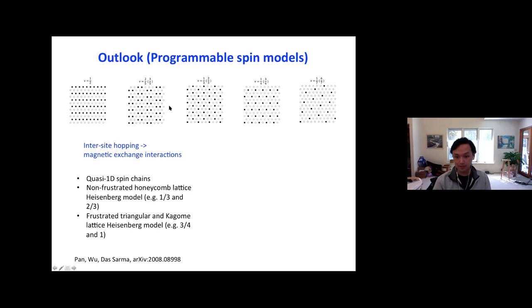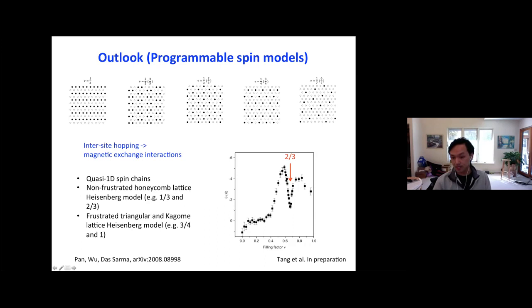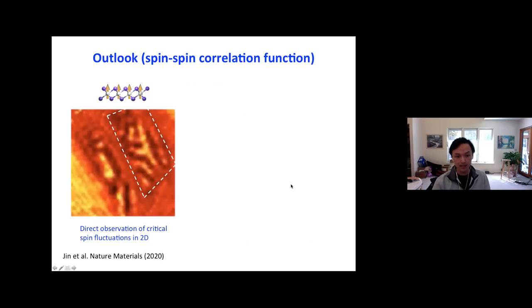And we recently measured the Curie-Weiss temperature as a function of filling more carefully, and you actually start to see a strong dip in the Curie-Weiss temperature at filling factor equal to 2/3 in one of the samples. And using the same polarization rotation imaging method, we have also directly imaged the critical spin fluctuation of a two-dimensional magnet.